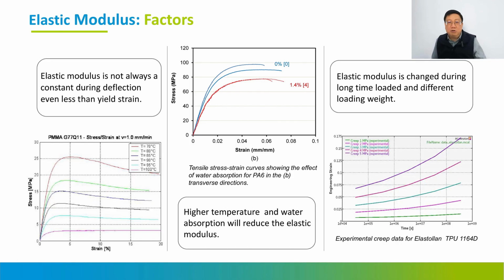If you choose a higher Tg and a more rigid material, then the elastic modulus will be more consistent, less affected by the environment, such as water, loading, and high temperature. That's the reason when we design the material, we want a higher Tg material. But higher Tg is much more difficult to process compared with the elastic material. So I would say if you use a higher Tg material, you can provide a more predictable elastic modulus.